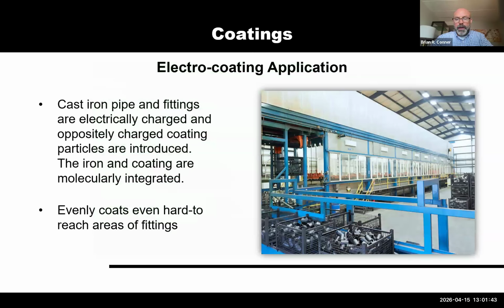Now, for our process, again, it's a 15-step process where we electrostatically charge with both opposite electrons and neutrons the coating itself so that it does adhere to the substrate. There's a bit of a cross-molecular bond that's taking place with the iron and the coating so that there's no chance for delamination and that the coating is applied evenly to every part of the pipe and fitting surface. And we've sort of perfected this over the last 12 years with the e-coat process that we use for our fittings. Since all of our fittings have been e-coated for a really long time, our Edge HP employs similar technology.